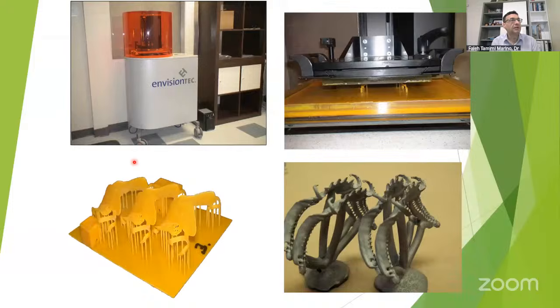These are some images from a company I used to work with in Montreal. It's called 3D RPD, and they're among the first people that started to print partial dentures. The way they did it is by printing the framework in something they call sacrificial resin. These frameworks are made of a resin that will burn in the furnace, and then they cast them, producing metallic frameworks for partial dentures that are cast. But these were only partially designed with the computer. This is done with a simple 3D printer called a stereolithography 3D printer, which fabricates the resin frameworks, and then we cast those frameworks.